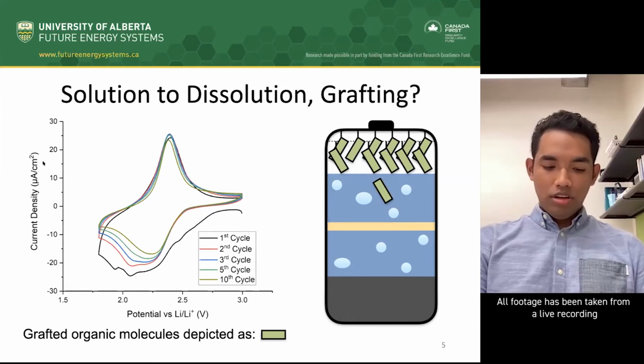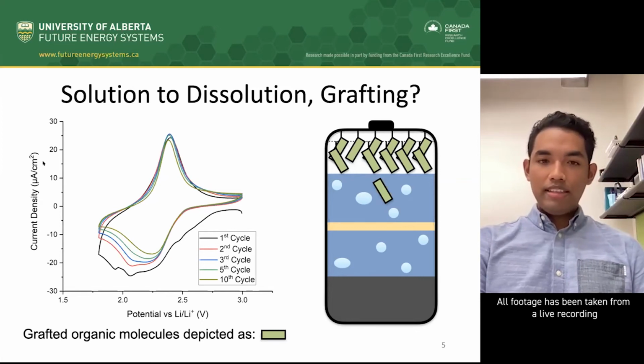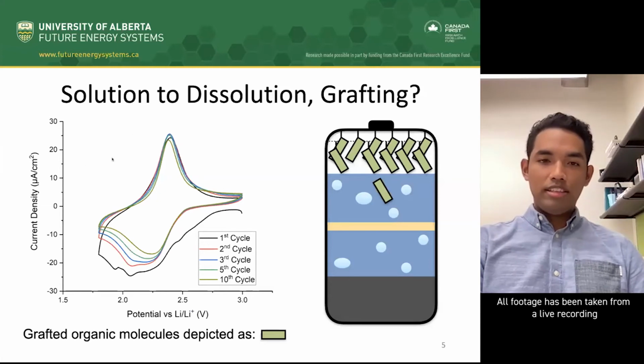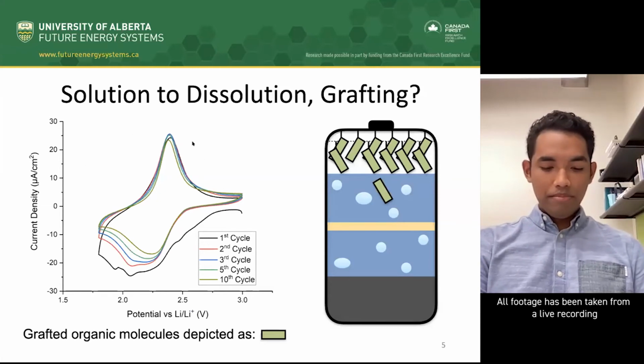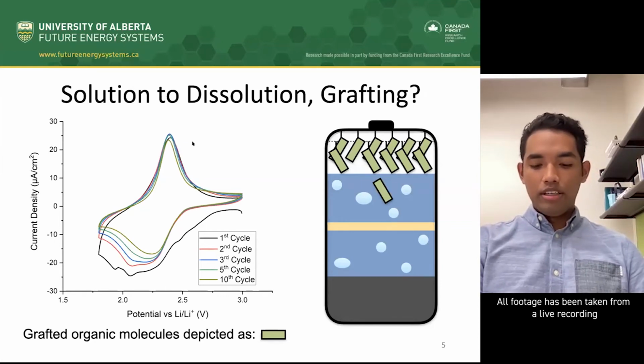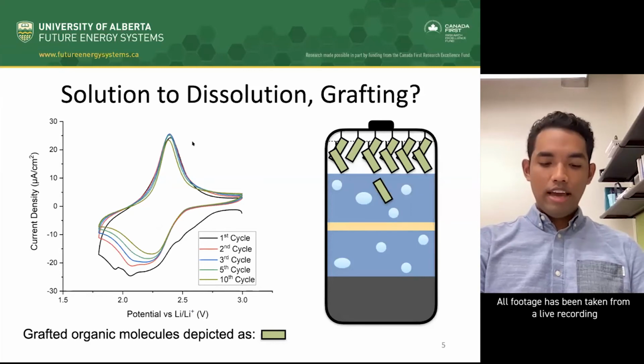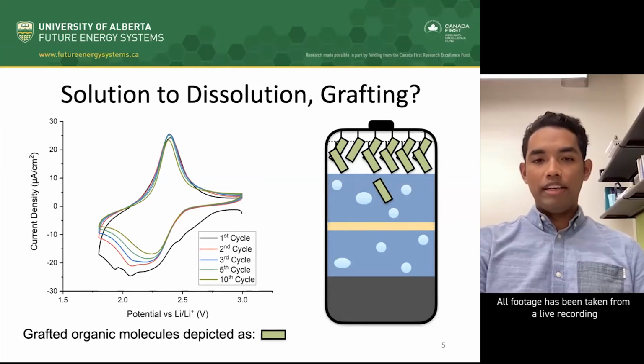Early experimental results have been promising, as we observe that this cathode architecture remains much more stable upon cycling, shown in the stable amplitude in our cyclic voltammogram over the course of multiple cycles. Future work will involve quantifying the stability of the cathode architecture through various performance tests and comparing these results to the non-grafted cathodes.